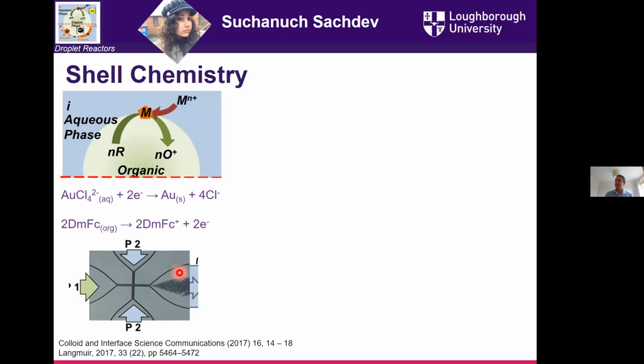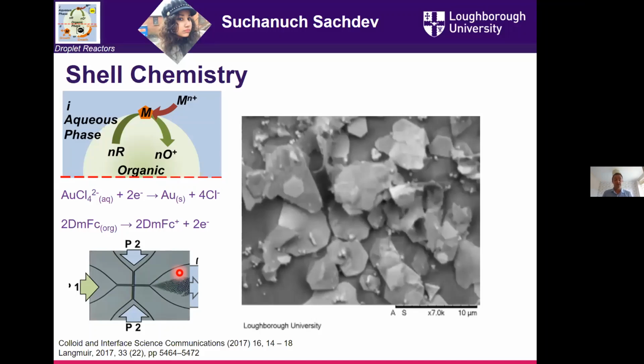So we made these droplets, and Nikita went off and imaged the products. So it was clear that we were making materials. When we were doing this, we could see the color changes, we could see particulates, we could collect them. And Nikita kept going down to the SEM, and more times than I would care to admit, would come back to me with images like this, and I would say, well, it's fantastic, it looks really interesting, but it's not what I imagined. I was picturing, I don't know, spherical particles or something that looked like a sphere. And I kept trying to convince her that maybe she hadn't washed the imaging stuff well enough, or there was something else on there, because as you do, you get set in your ways, you have this specific vision of what you thought was going to happen, and it wasn't that.